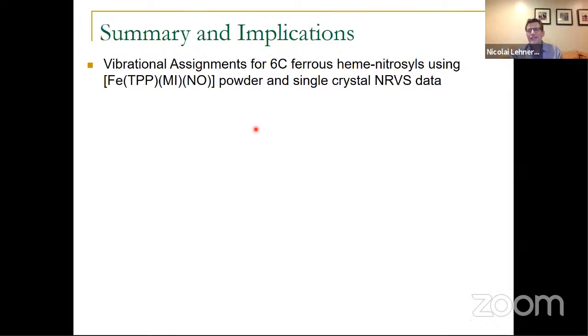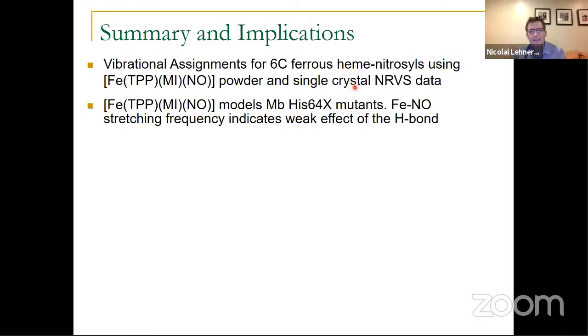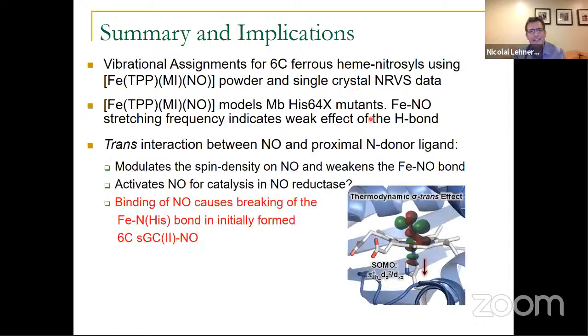All right, so here's my summary. So I showed you that we were able to get vibrational assignments for the 6-coordinate ferrous nitrosyls using this technique called NRVS, and we're using single crystals to do this, and we can assign our spectra. And the most important thing is that we can now analyze the trans interaction between NO and the trans ligand, the imidazole.